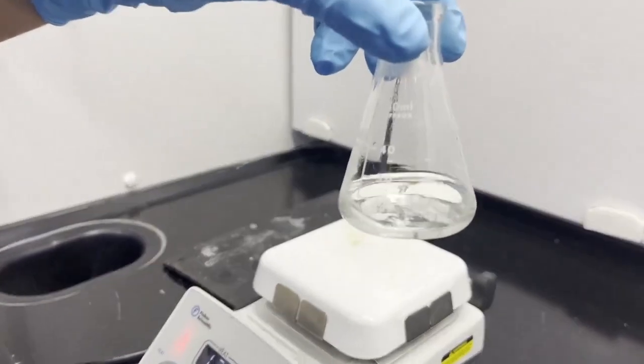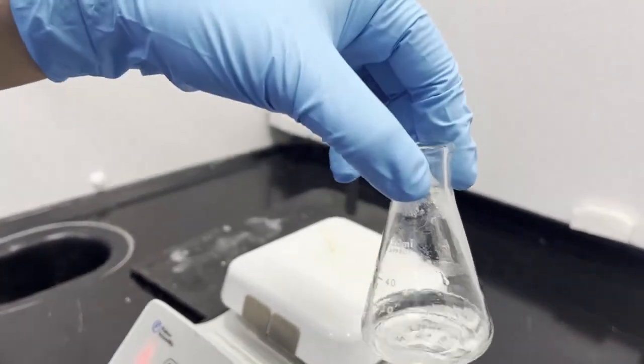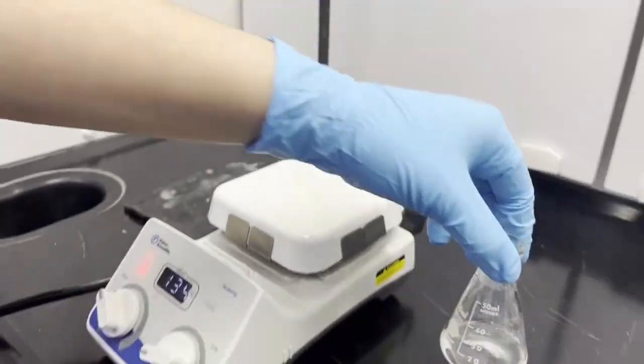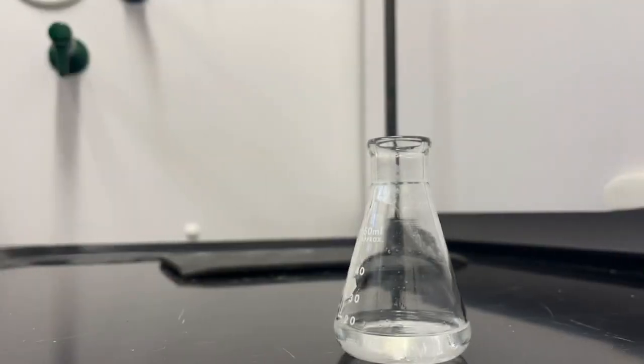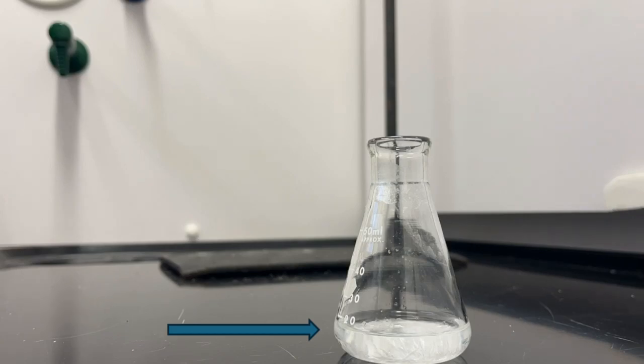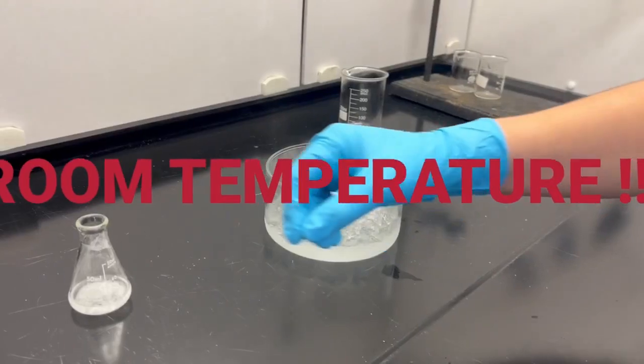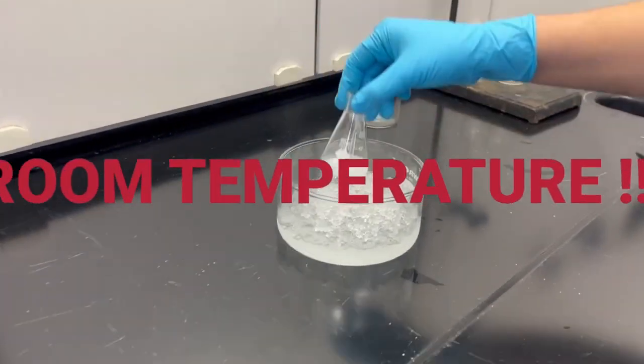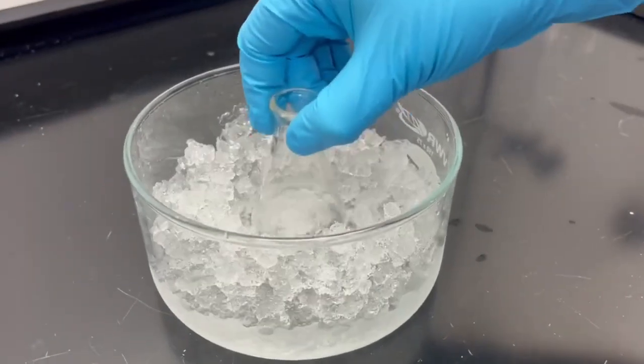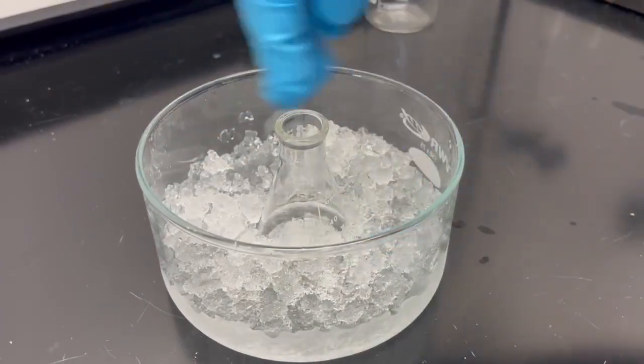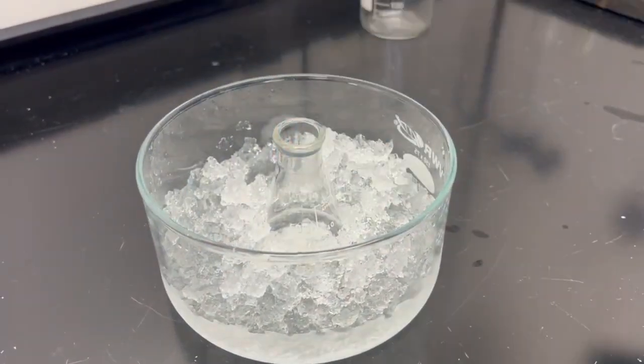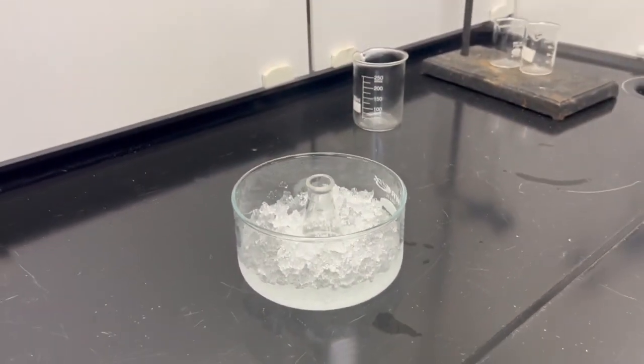Once dissolved, begin cooling the solution to room temperature. While the solution is cooling, crystals should begin to form at the bottom of the beaker. Once it is cooled to room temperature, place the flask into an ice bath to continue cooling until you see no more crystals are forming. Also, it's important to know that the slower the cooling process, the purer your resulting crystals will be, so be patient.